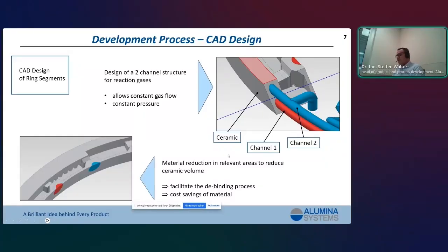And here you always have to take care about the material reduction in these special relevant areas, to reduce the ceramic volume, because this later on facilitates the debinding process and will give you cost savings for the material of the whole ring.